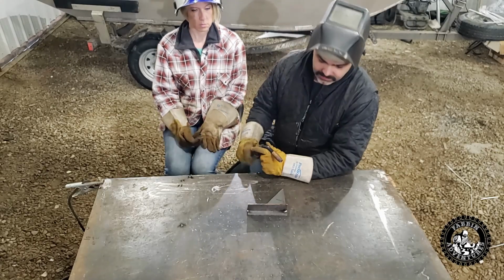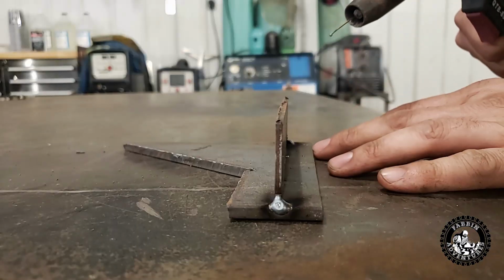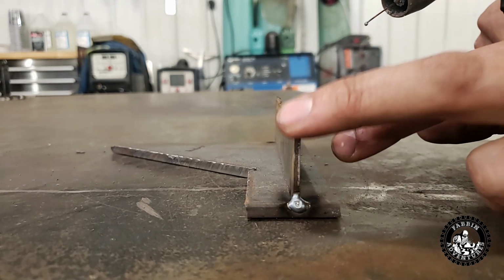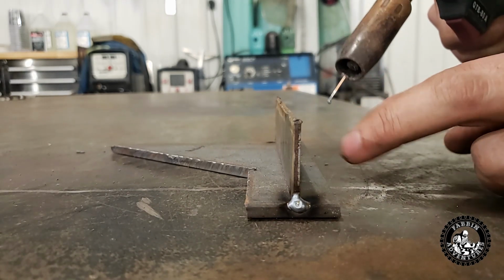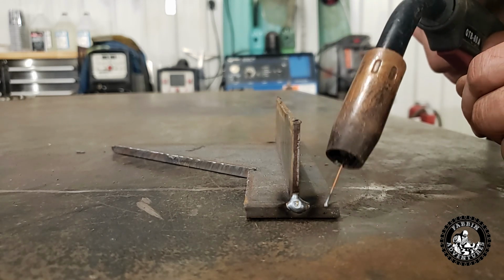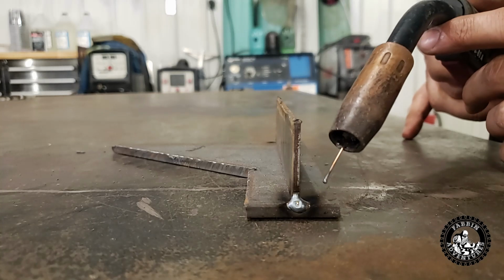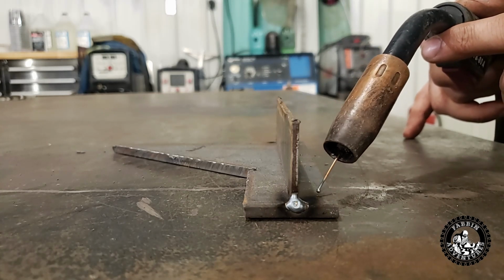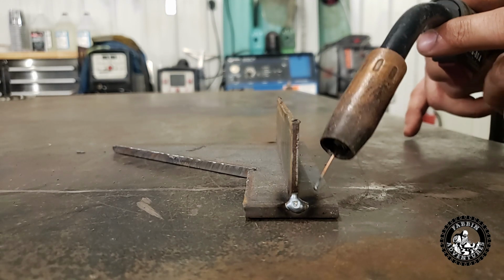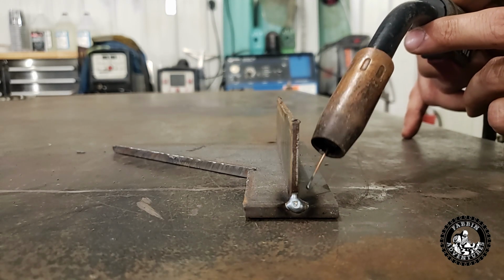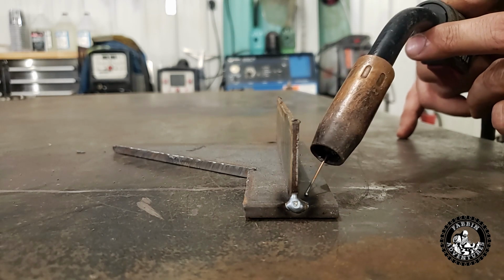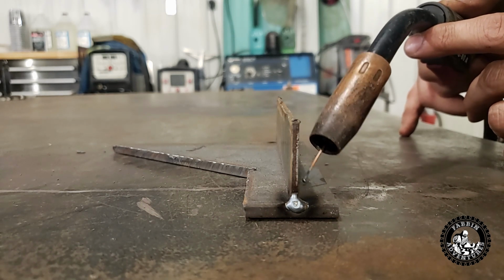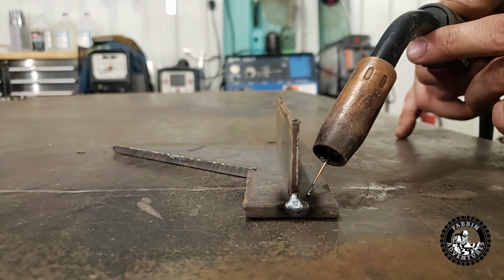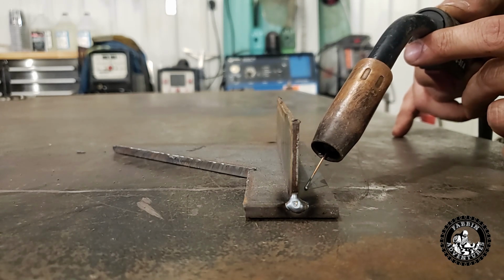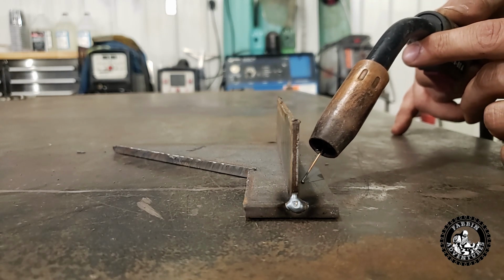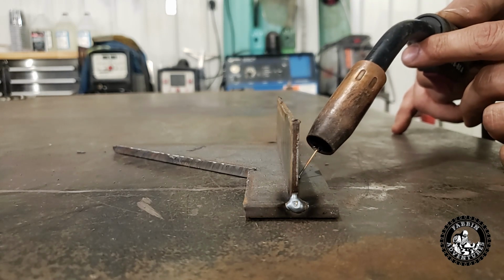So this is thick to thin welding. We're going 1/4 inch to 1/8 inch when you're welding something thick to something thin. Typically you set your welder for the thick, for 1/4 inch. This is 1/4 inch, this is 1/8 inch. So I would set my welder for 1/4 inch or 3/16, just under the 1/4, and you would spend a lot of time on the heavy plate, and then you would just touch the light plate real quick. So you go real slow on the heavy plate and then just touch the thin one. If you spend too much time on the thin one, you're going to blow a hole through it real easy.